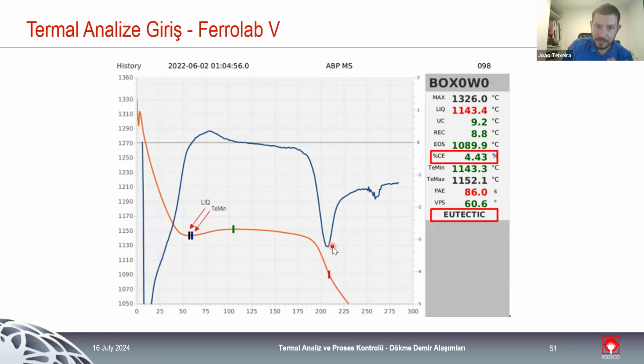And the main reason why this is not good is that at this point, we already have a lot of austenitic structure formed in the cast. So even if you have a lot of expansion, it's not enough to compensate the amount of austenite that we already have formed. And the graphite should always happen more at the eutectic point to counteract the contraction of the austenite. So the way that we have to improve VPS is by having a better inoculation. So it's to promote an early formation of graphite.